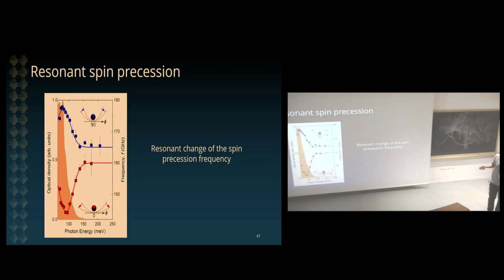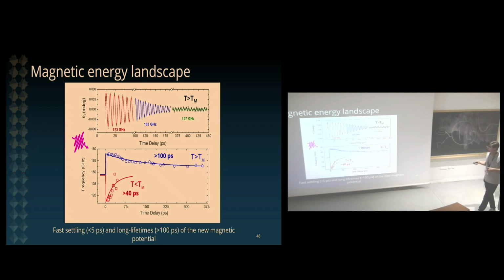You can do this experiment at various photon energies, in the high temperature phase and in the low temperature phase. And you see systematically that as you approach the phonon resonance, you either soften your potential or you harden your potential, depending on which phase you are in. Okay, so this is telling us something important. We are changing the magnetic energy landscape when we are exciting the lattice, when we create this out of equilibrium crystal structure. So importantly, we need to establish how long it takes to go back to equilibrium.